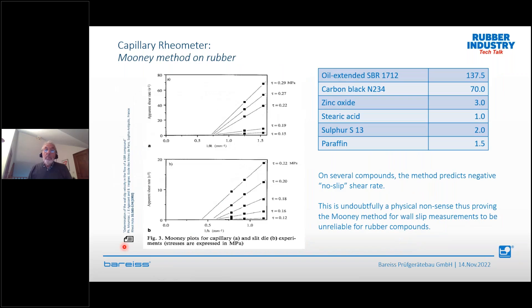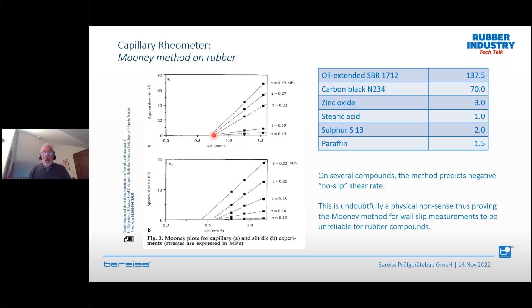It must be stressed that the Mooney method was developed essentially for thermoplastics, not rubber compounds. When rubber scientists tried to use it on rubber, for a very large number of compounds — one published example being an oil-extended SBR with standard carbon black tested by capillary or slit-die rheometer — the method predicted a negative no-slip shear rate, which is complete physical nonsense. So for rubber compounds the Mooney method is not reliable at all.